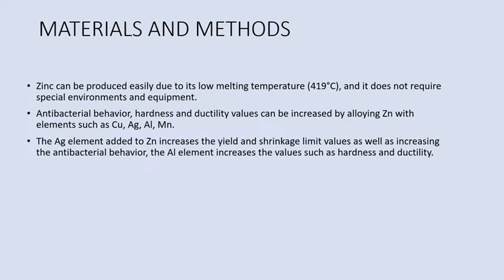And materials and methods. As I mentioned, we use zinc because zinc has a low melting temperature, which is 419 degrees Celsius, and it's very easy to produce. It does not require special environment equipment. Pure zinc's mechanical properties and other properties are rather low. In order to increase them, we alloy zinc with elements such as copper, silver, aluminum, manganese. In my work, we use silver and aluminum. Silver increased zinc's yield and shrinkage limit values, and it also increased its antibacterial behavior. And the aluminum element increased values such as hardness and ductility.